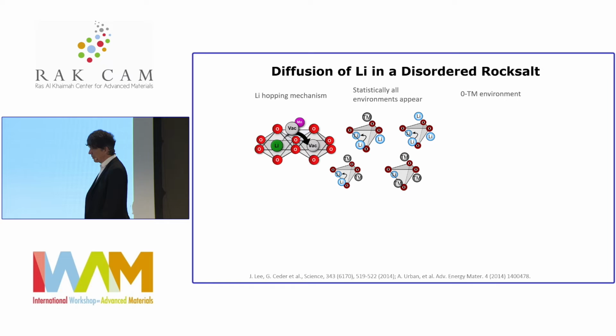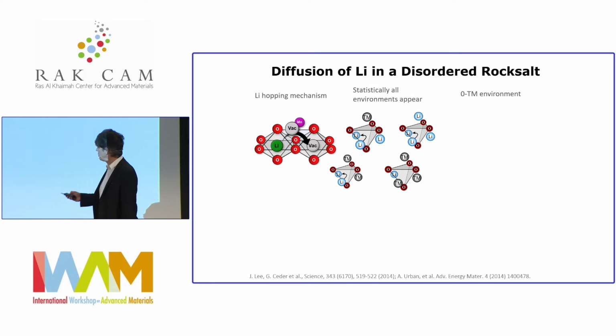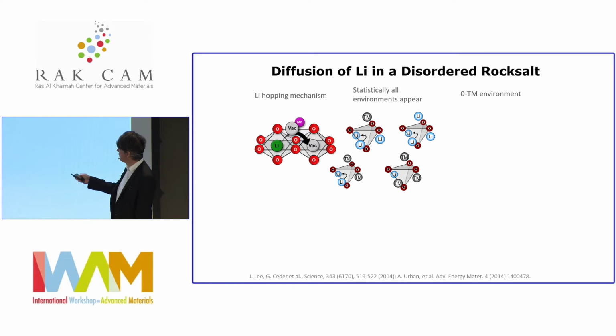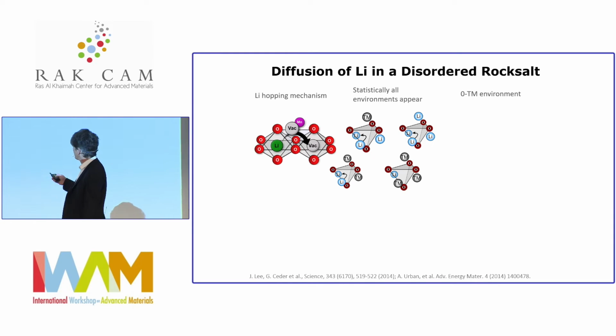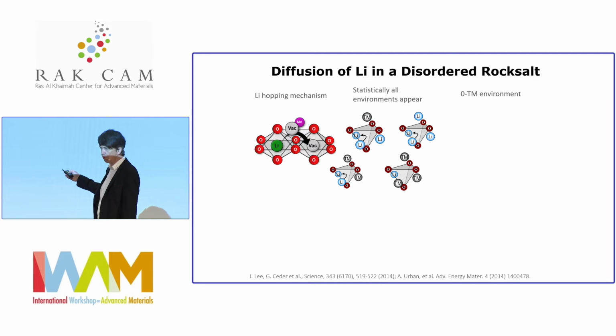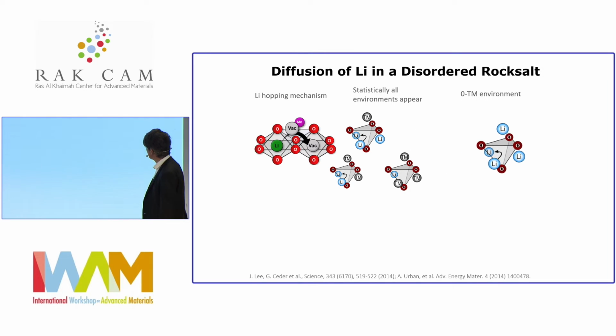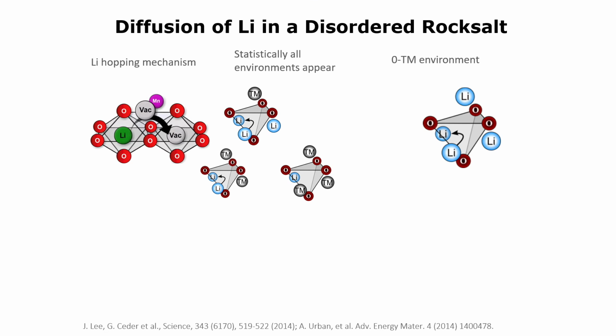And what happens if you have disorder? Now you essentially have statistically all kinds of environments around the activated state. So in a layered material, you only have this one, and this one. But now we randomly distribute the ions, so we also, for example, have this environment, only lithiums. And if you look carefully, remember I told you the electrostatics is the problem for lithium diffusion. Here, the electrostatics will be much better because when lithium goes through the tetrahedral site, say this is a vacant site, and typically we have divacancies, it will only see another lithium.